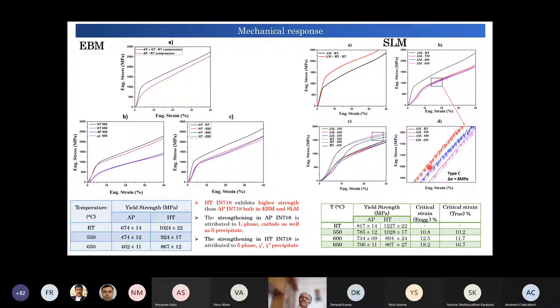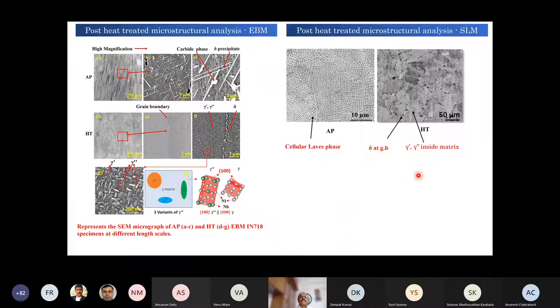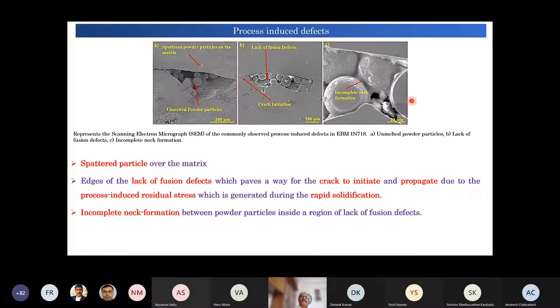Those who have worked on steels know that there is a PLC effect in steel, which leads to serration in the stress-strain curve. That we could very closely monitor in the selective laser melted process, which was absent in the case of the EBM process. And it has some consequence in some properties. Post heat treatment, the same heat treatment given to both the materials has led to different microstructures, different locations of precipitates, right? So all these things would influence the targeted properties definitely.